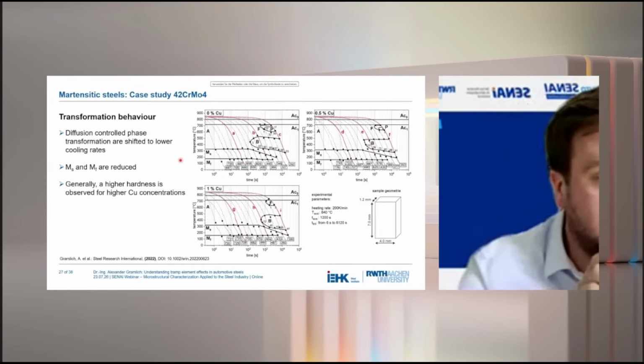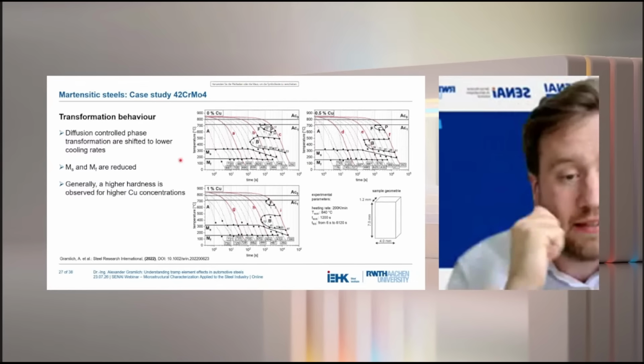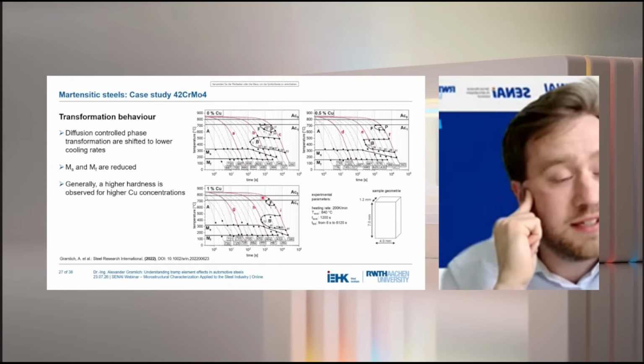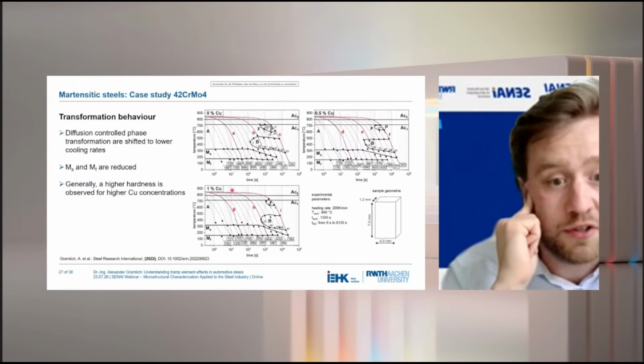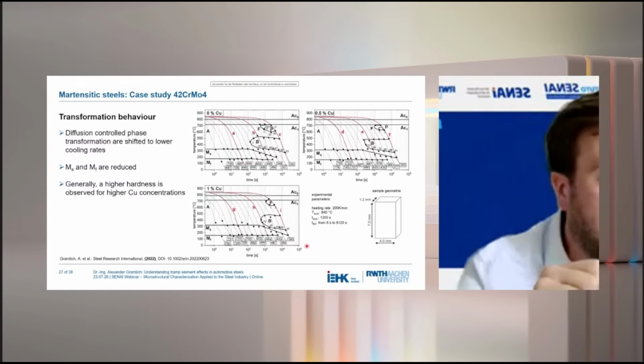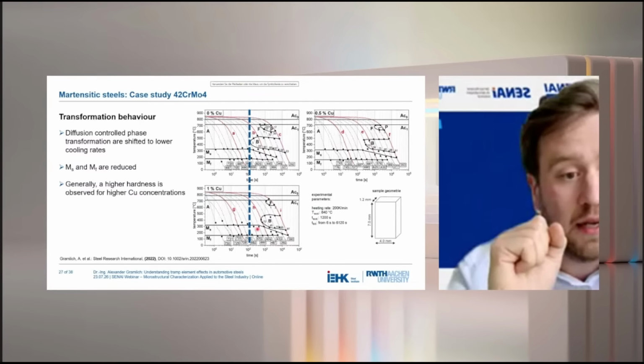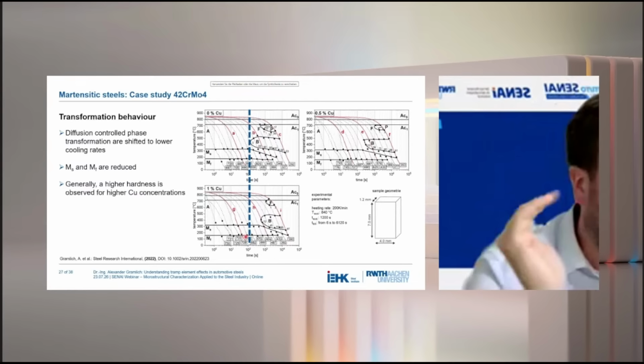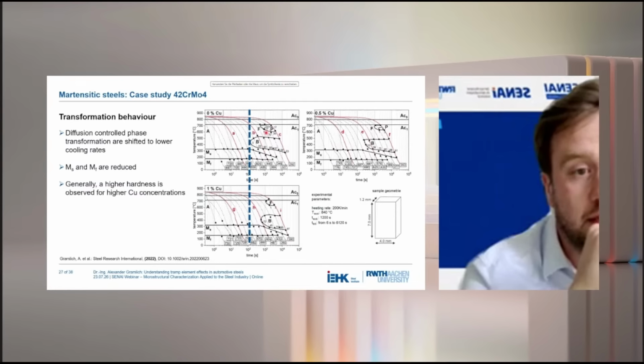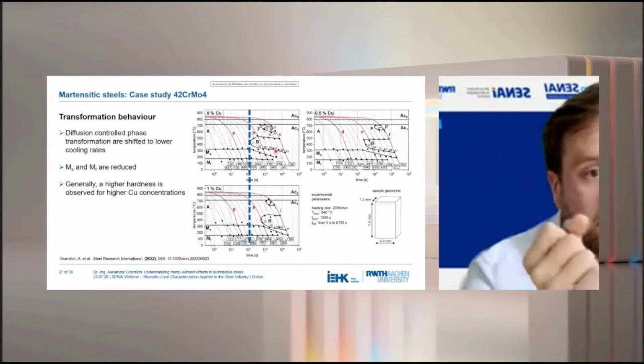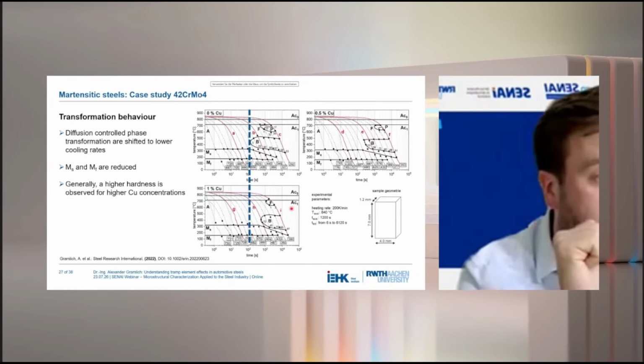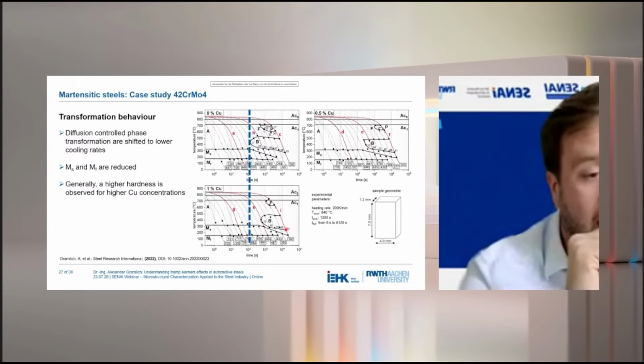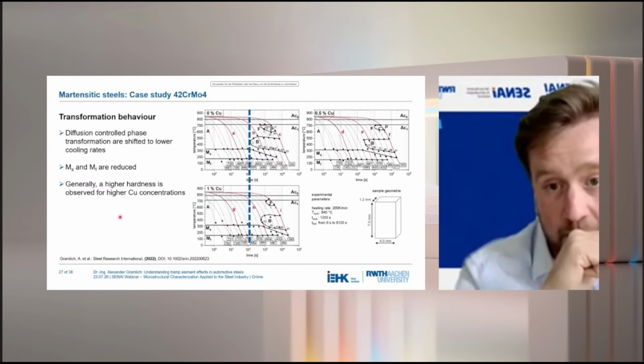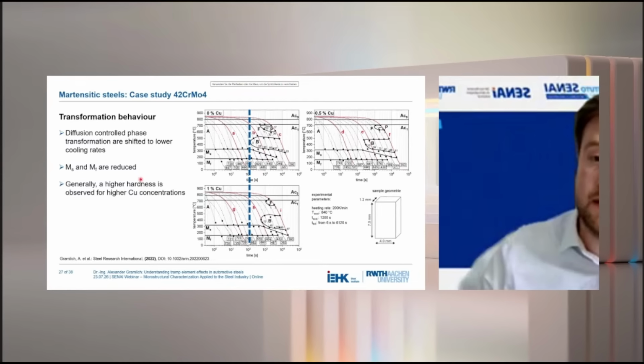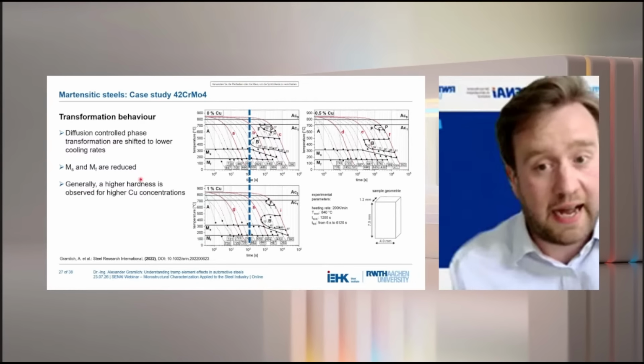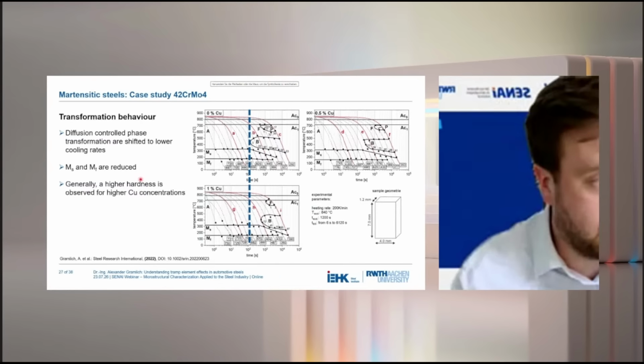For this, we collected standard CCT diagrams. As you can see in this slide, we have here the reference state and then the CCT diagram for 0.5% and for 1% of copper. And as you can see here quite directly, but I'm adding a line here to make it even more visible, all of our diffusion controlled phase transformations are moved to the right side. So bainite formation is now taking place at slower cooling rates, the same as ferrite, and we couldn't even find any pearlite formation anymore. So we see here basically hardenability is increased through the 1% of copper. Additionally, we see that martensite start and martensite finish are reduced. And generally, we see a higher hardness in dependency of the copper concentration.